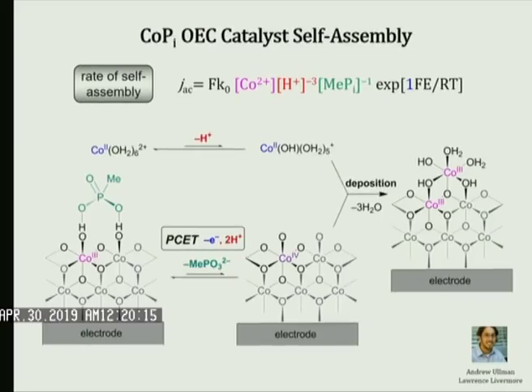Then this poor student, I told you we just oxidized cobalt to cobalt-3 and it lays down on the electrode. He literally spent 5 years of his life to figure out what really happened. It's what you guys fund. And it took 5 years of his life, and he figured out that you do oxidize cobalt-2 in solution, but it's through this complicated reaction sequence that involves 3 protons. You need cobalt in solution. And then we had phosphate around our catalyst, and the phosphate has to dissociate. And then that allows a cobalt-2 to get oxidized by a cobalt-4 to make the cobalt-3,3.